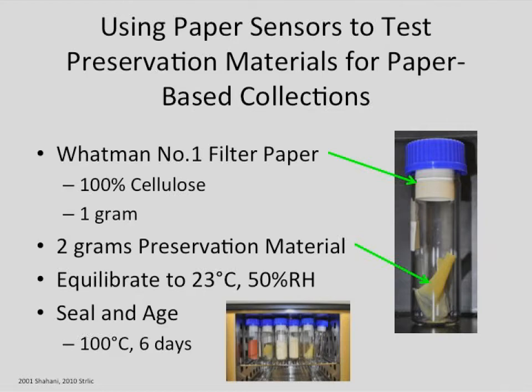We put a couple grams of the preservation material at the bottom. There's no moisture or water in there, other than we pre-equilibrate the vial to 50% relative humidity in our temperature-controlled room for several days before we seal it with a silicone rubber O-ring. We've leak tested these jars. They're not leak proof, but they're the best jars we've got.